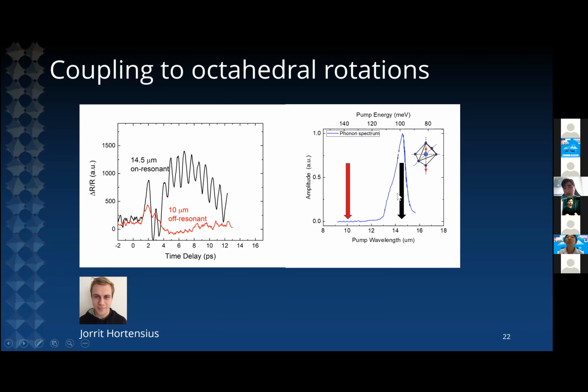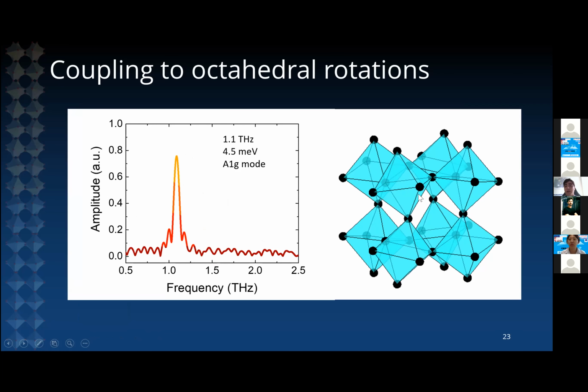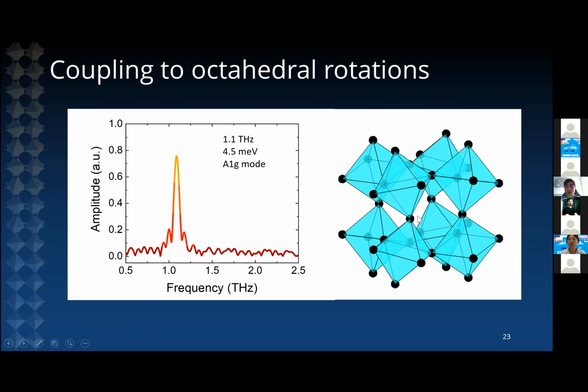So if we excite our material resonantly with these phonons, we see in the reflectivity this pattern of oscillations. So this is an oscillation around 1 terahertz, which corresponds to an oxygen octahedral rotation. On the other hand, if we excite the crystal of lanthanum aluminate off resonance, the specific case at 10 microns, we do not see this oscillation at all, and there is a rapid decay of the signal. So this particular oscillation reflects the activation of this Raman mode, which is visualized in this animation here.